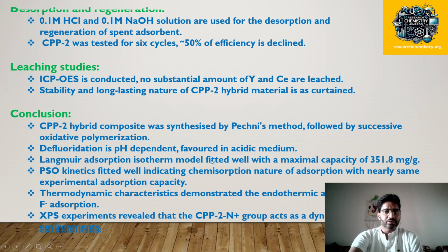Langmuir adsorption isotherm model fitted very well with a high maximum capacity of 351.8 milligram per gram. Pseudo-second order kinetics fitted well, indicating the chemisorption nature of adsorption, with nearly the same experimental adsorption capacity. Thermodynamic characteristics demonstrated the endothermic and spontaneous nature of fluoride adsorption. XPS experiments revealed that the CPP2 N positive group acts as a dynamic adsorbent in acidic environments.